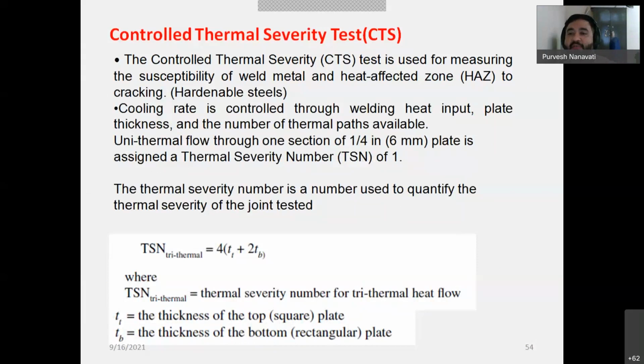So, controlled thermal severity test, I'll explain briefly. When the heat source is moving, the plate is throwing out the heat, right? Depending on the section thickness, there is a thermal severity number, TSN. So for a 6 mm plate thickness, TSN is considered by standard to be 1.